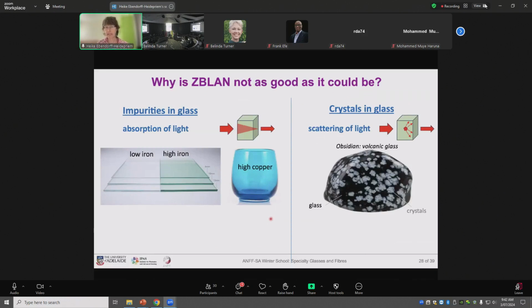So why is ZBLAN not as good as it could be? Two reasons. One, it has impurities in the glass, transition metal ions like iron or copper. And so I got funding from the Australian Research Council to work on the purification of the glass raw materials here on Earth to get rid of iron, copper, and other contaminations in the raw materials. The other side of this story is the crystals in glass, because they cause scattering. What you can see here is obsidian, a volcanic glass, a natural glass, and over millions of years these snowflakes have formed, crystalline silicon dioxide, which has a white color. And this is not what we want to have in a glass because it causes scattering.